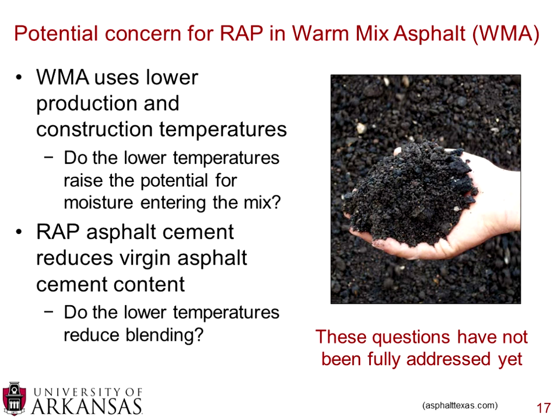As I mentioned, the RAP is generally added later in the drum, and because it's added later in the drum, you are actually decreasing the amount of time the RAP is within the drum, and you're decreasing the amount of time that the moisture has in order to potentially evaporate. So some moisture issues can come up.